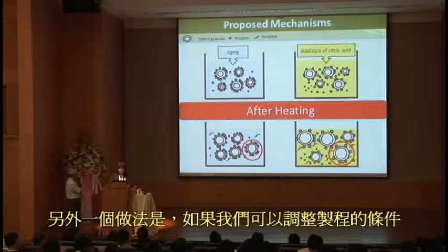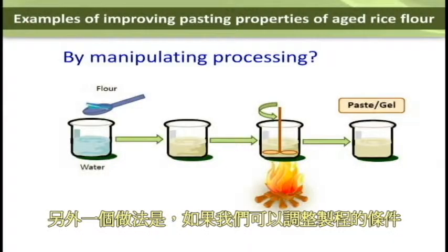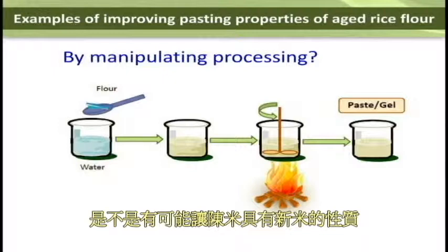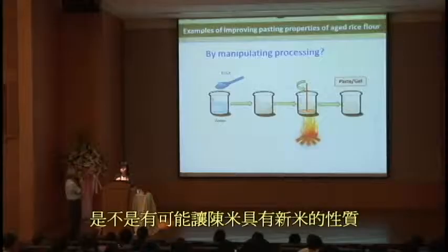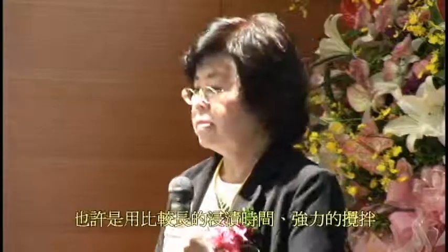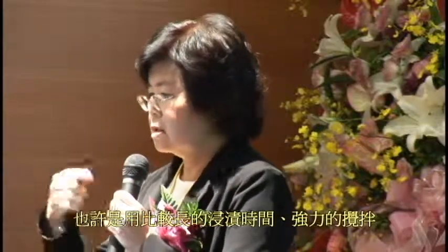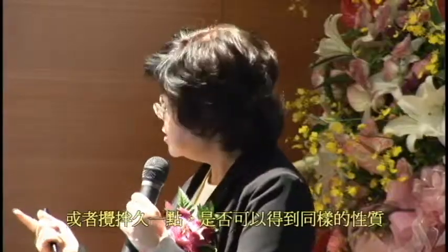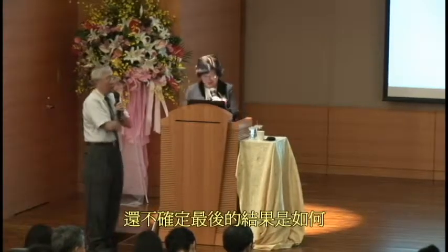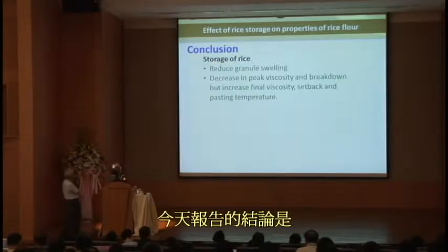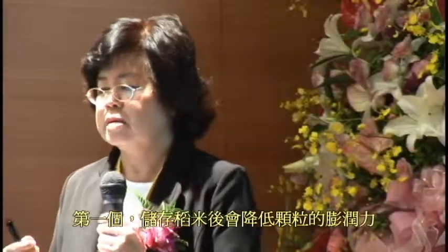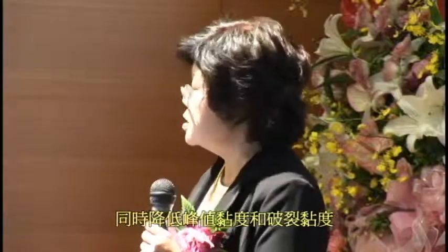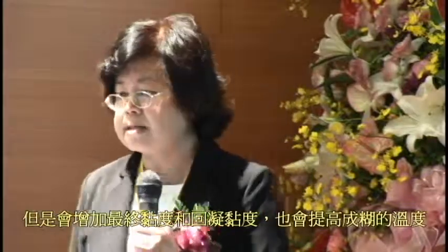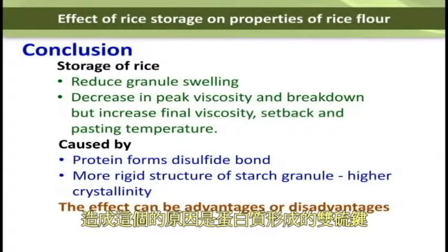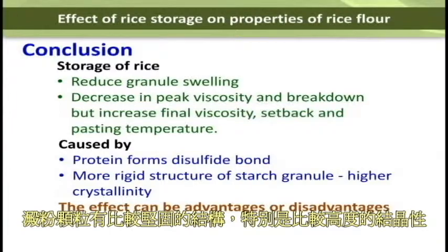Another experiment going on in our lab is this: if we don't want to use any ingredient, but we manipulate the process, is it possible to change aged rice flour to be close to new rice flour? Maybe by a longer soaking time, a higher stirring speed, or longer heating. We are not sure what the final result will be. So the conclusion of this presentation is that the storage of rice reduces granule swelling, decreases peak viscosity and breakdown, but increases final viscosity, setback, and pasting temperature. And this effect is caused by protein through disulfide bonds, a more rigid structure of the starch granule, or high crystallinity.